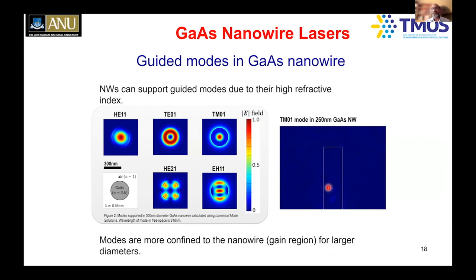Here we are showing the TM01 mode, which has the highest field intensity at the core of the nanowire, in a nanowire about 260 nanometers in diameter. Depending on the optical modes you're looking at, such as the TE01 mode and the HE11 mode, the various optical modes have various shapes. Depending on the particular kind of laser, you need to choose the particular optical mode to make these lasers.